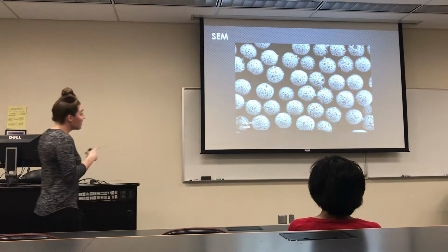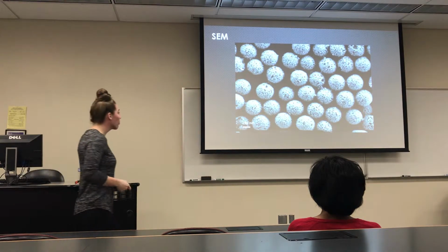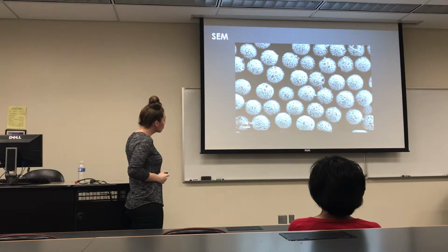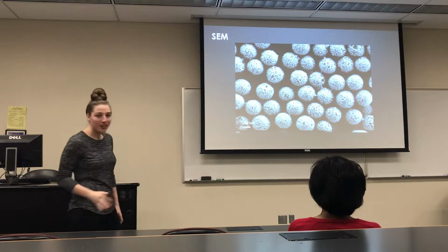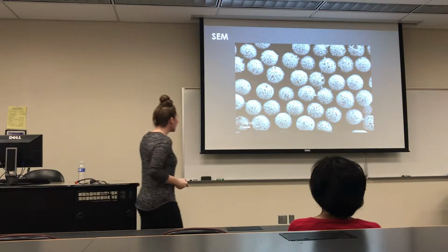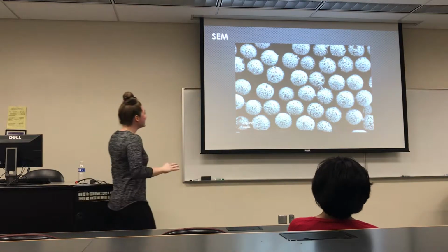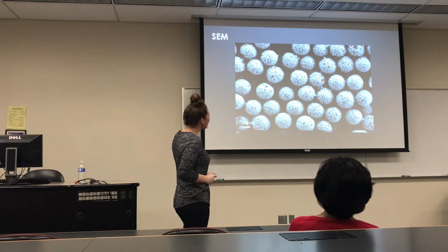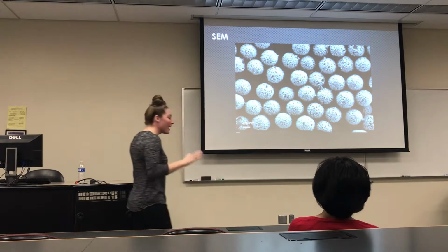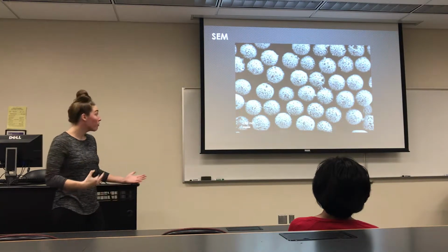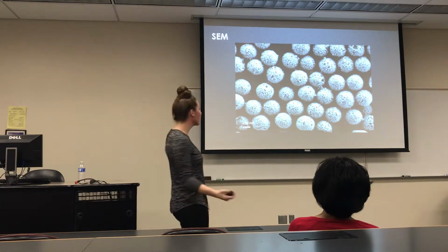So if we go and look at the SEM, we can confirm that we actually have gold bound. So all this white is gold that is bound to our silica nanoparticle, which is really, really cool. I'm a nerd, so it's so cool to see this, but we can still see some gaps. So we don't necessarily have full shell coverage, which is what we want if we want to move on to our biomedical application.